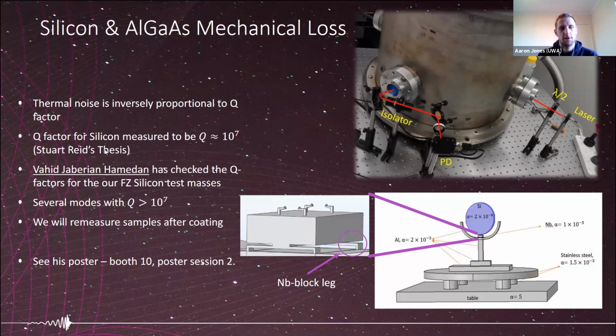This has also been measured in the past, and we also saw Disha's talk on measuring mechanical loss in silicon. We've measured this to be 10 to the 7 for our samples. And so you can see some of Vahid's suspensions and a picture of his optical setup up here on the top. We're going to remeasure these samples after coating and see if we get any substantial change in our thermal noise, which we hope we won't. We don't expect it.